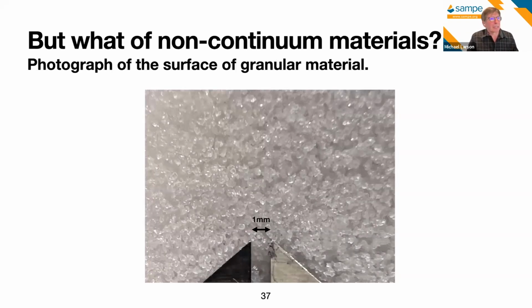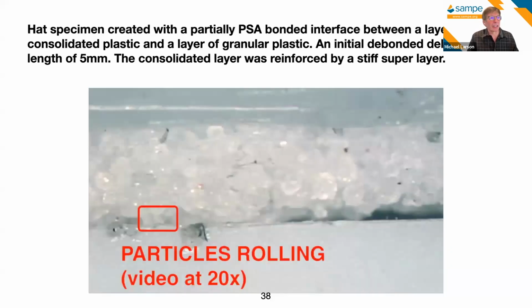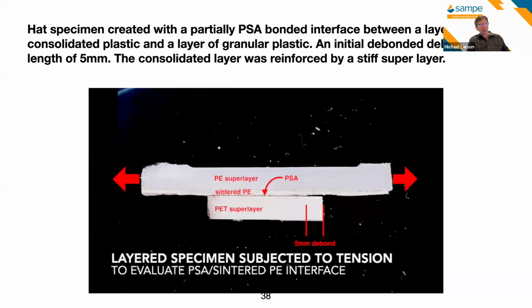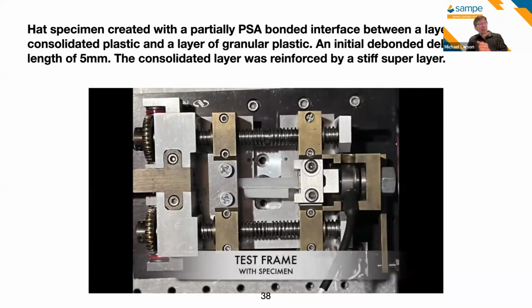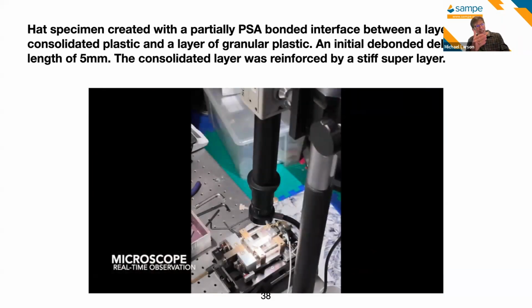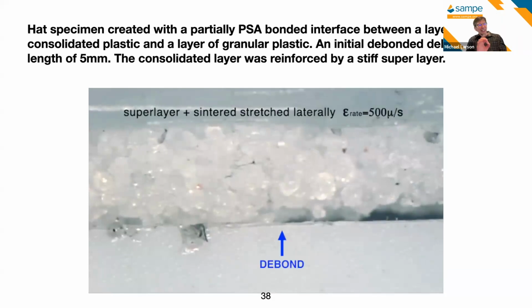And when we did some experiments with some of these more particulate materials that are held together with structures, we've got a little video here to show. We created a hat specimen to drive things in a mixed mode way, not unlike our specimen, and pulled on it. So this is what the specimen looks like. We've got a PSA in between some layers. You put this in a test frame and pulled on it, and then with a high-powered microscope, looked at the leading edge of the delamination or debond.